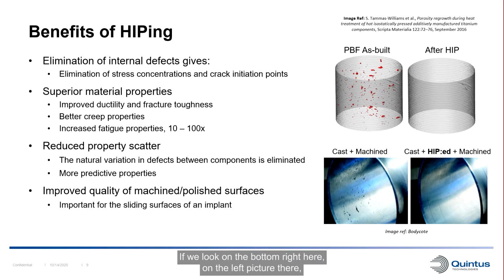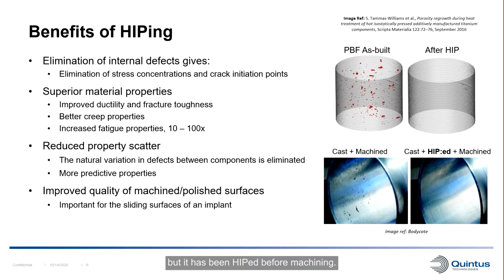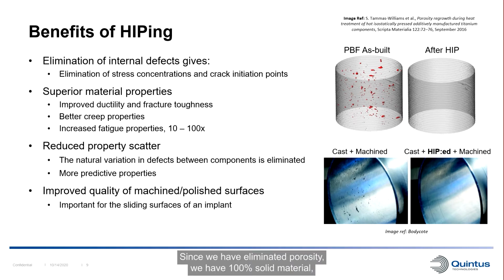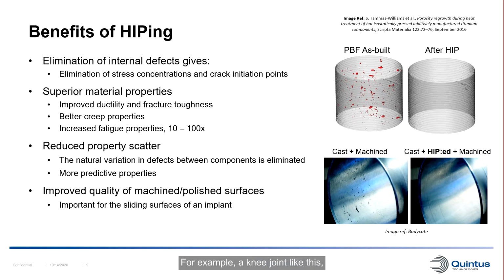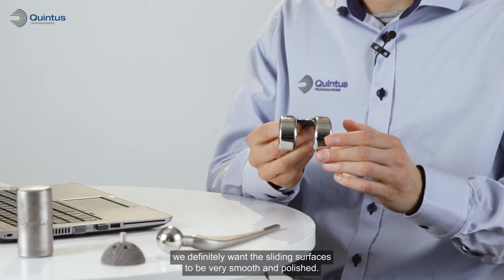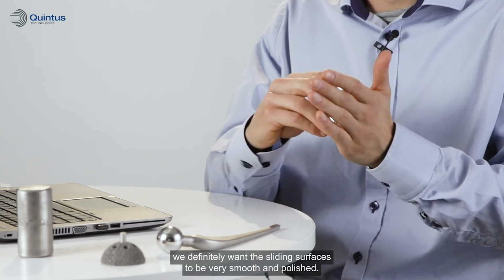If we look at the bottom right here, on the left picture we see a cast tube that's been machined on the inner surface. And as we can see, some of that internal porosity has been revealed in the machined surface. On the right of that picture, we have the same type of cast tube, but it has been hipped before machining. Since we have eliminated porosity, we have 100% solid material, we don't get any surface porosity in that machined surface. And this can be quite important when it comes to medical implants. For example, a knee joint like this, we definitely want the sliding surfaces to be very smooth and polished.